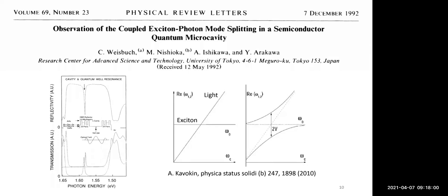And since this pioneering work, there have been a number of different associated excitonic phenomena that have been shown, like Bose-Einstein condensation, superfluidity, polariton lasing, spin switching, and so on. And all of them have been discovered in conventional solid state microcavity semiconductor systems. But owing to the small binding energy of the excitons in traditional inorganic materials, for example gallium arsenide, most of these effects can only be observed at cryogenic temperatures. And this makes cavity polaritonics in these systems quite impractical for real device applications.